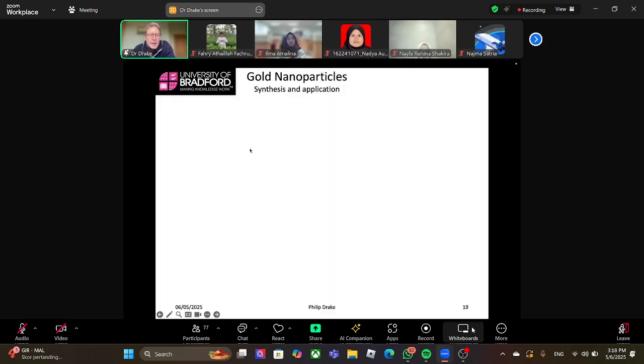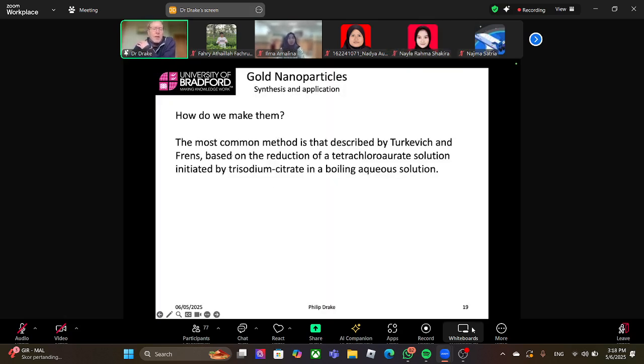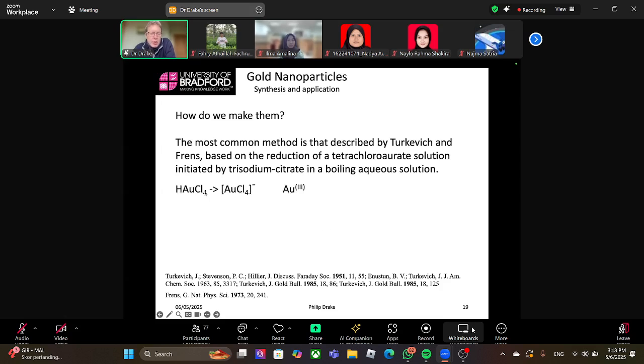So how do we make these particles? The most common method is described by Turkevich and Frens. It's based on the reduction of tetrachloroaurate solution, initiated by trisodium-citrate in a boiling aqueous solution. So you take gold chloride, ionic gold, gold 3 plus, 4 chlorines gives you a minus charge on the ion with a proton stabilizing that. So it's metallic, ionic gold 3 plus.